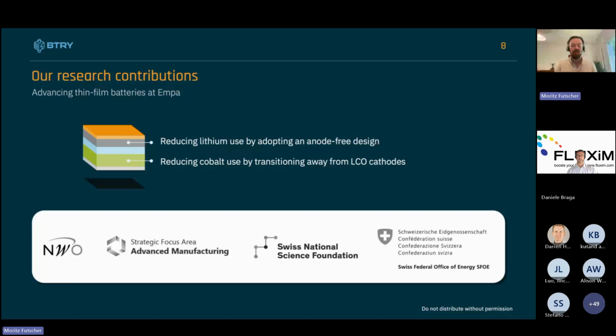Now this is from the research side. So what we have done at the thin film solar cells, the laboratory for thin films and solar cells at Empa. And I would especially like to focus on two key research works which we did. On the anode side, where we reduced the amount of lithium by going for an anode-free design, and I will explain in a bit what this actually means. And on the cathode side, by reducing the amount of cobalt in the cathodes by transitioning away from lithium cobalt oxide cathodes, which is the most frequently used cathode in thin film batteries, but also in classical bulk batteries.